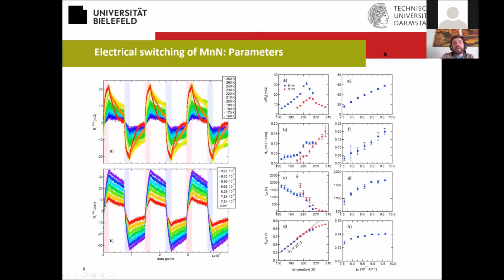Okay, second, let's have a look at the right column, which corresponds to the bottom graph here. So we look at the current density dependence. So we see that as we increase the current density, so this is always the current density in the platinum film, from 7.5 to nearly 10 times 10 to the 11 amps per square meter, we see that the amplitude of the switching goes up. You see this nicely here. Correspondingly, the efficiency of the switching, so this initial slope also increases, no surprise here, and the corresponding energy barrier is essentially flat, which means that there is no big change in the relaxation times that we see here. But as we go to higher current densities, we see that the relaxation times do increase to some extent.